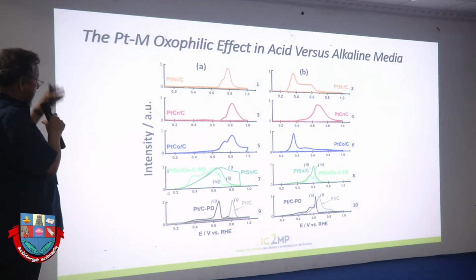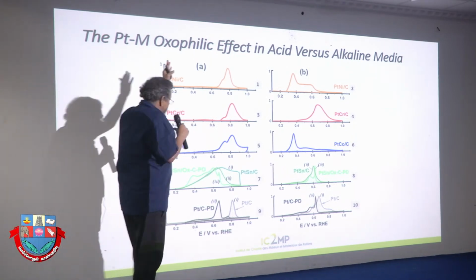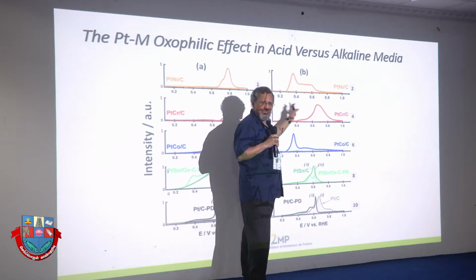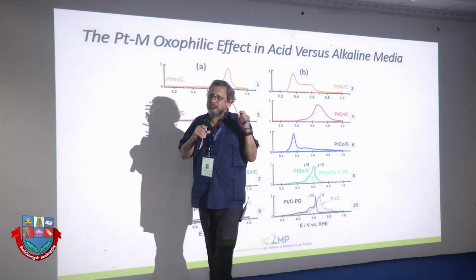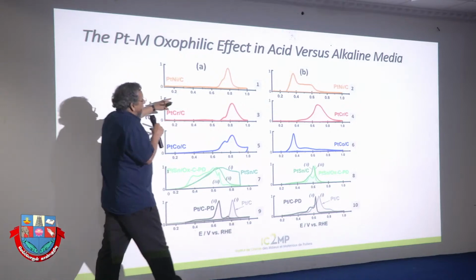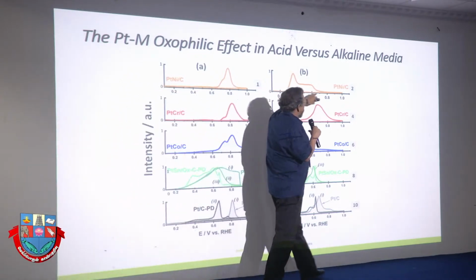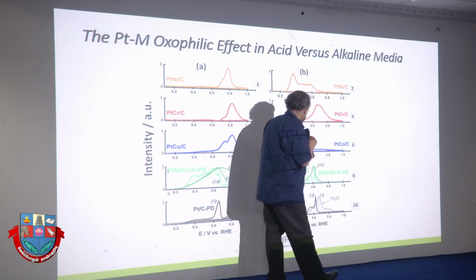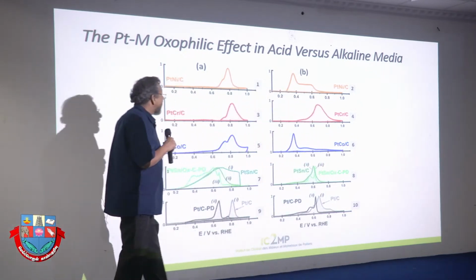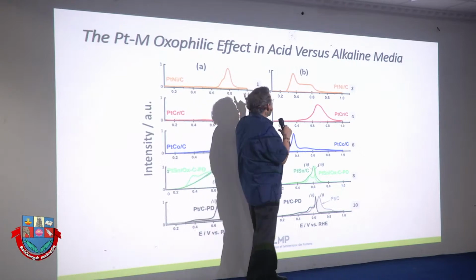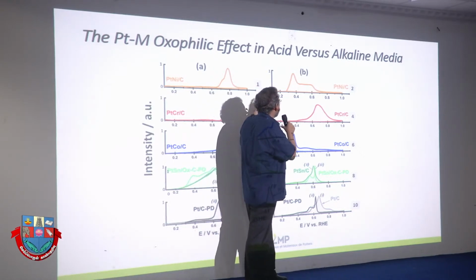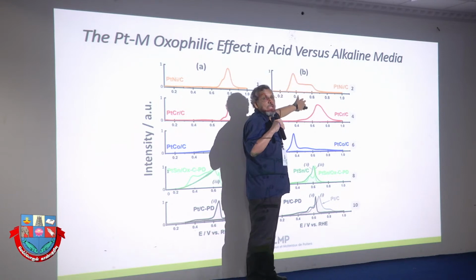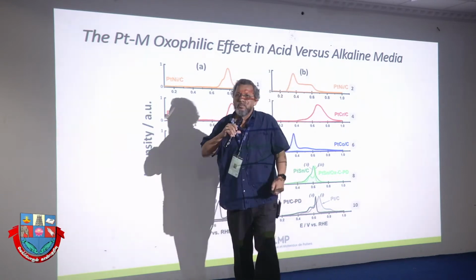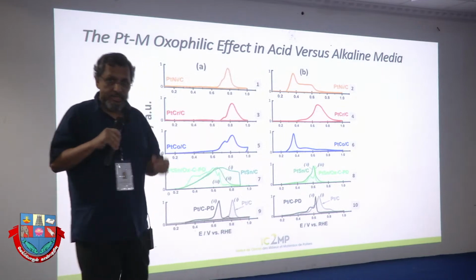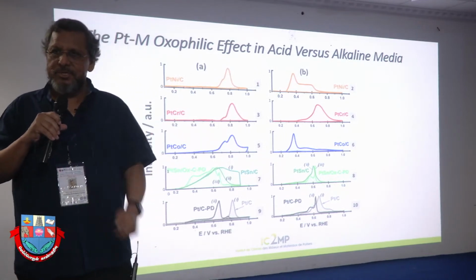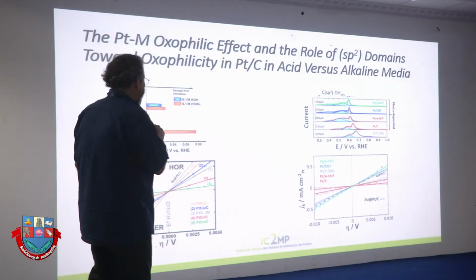Now here I summarize all these guys. That is in acid and that is in alkaline. And look at the difference that happens when you change the electrolyte. So here you see the effect of the partner. Here is nickel, chromium, cobalt, etc. And if you do the experiment of hydrogen in acid and alkaline, you will see that this part actually favors the catalytic activity of platinum. Because the catalytic site is actually platinum, not nickel, nor chromium, etc.